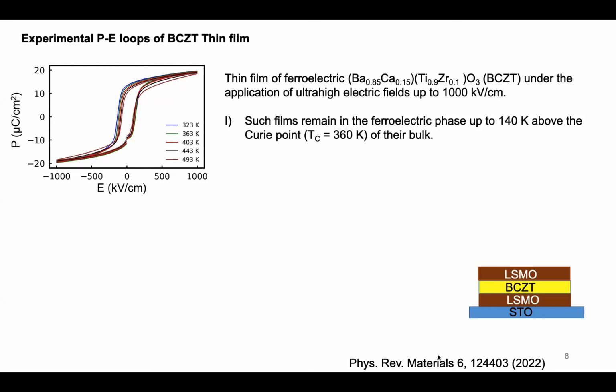And the interesting part here is that you can see that the temperature that they were able to get the P loops is up to 500 Kelvin. And still the films were in the ferroelectric phase. The P loops are not closed. The area in the loops is not closed, which means that the films are still in the ferroelectric phase, which, at 500 Kelvin, is 140 Kelvin above the Curie temperature of the bulk.